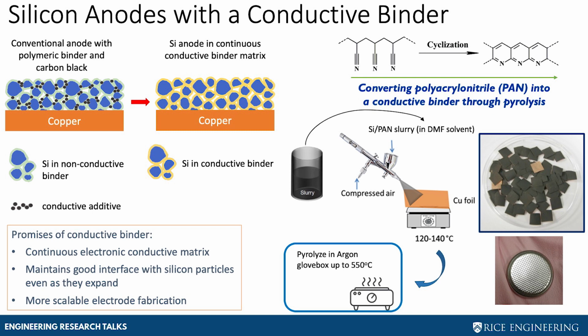What's nice about this is that it's a polymer that is very viscous. We can mix it with our silicon, but it goes through what we call cyclization when you pyrolyze it. So we take it up to a higher temperature, and that pyrolyzes it, and that makes it highly conductive. So what's nice about this process is we can make a slurry, coat it on copper foil, pyrolyze it, and then we have our battery anodes on here. And we'll then go ahead and make coin cells with it. And really, this conductive matrix is really electronically conductive. And so that's why it was really, really effective.